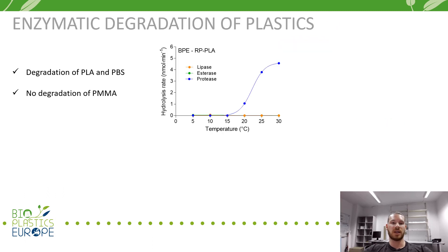Here, we show the results from measurements of the enzymatic degradation of two biobased polymers and one conventional petroleum-based polymer. Both biobased polymers were hydrolyzed by digestive enzymes. Polylactic acid, or PLA, was hydrolyzed by a protease, but not by lipase and esterase. The hydrolytic activity of the protease increased with temperature to a maximum at about 25 degrees Celsius.